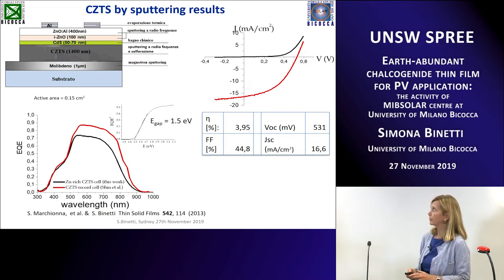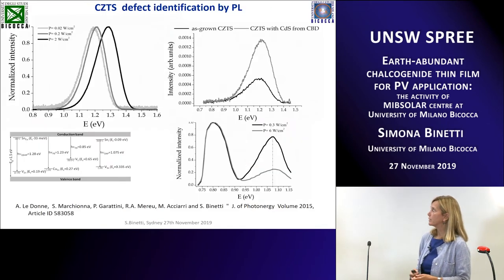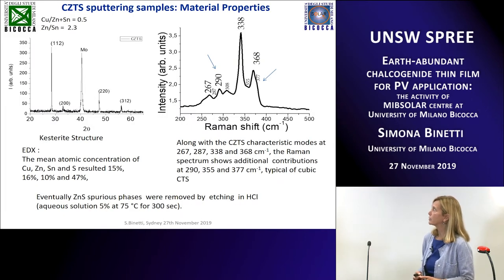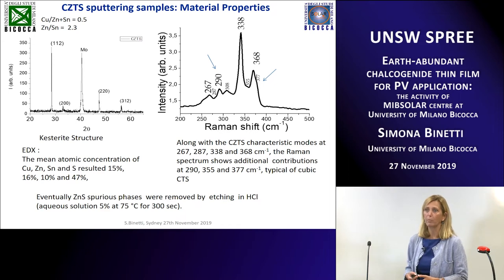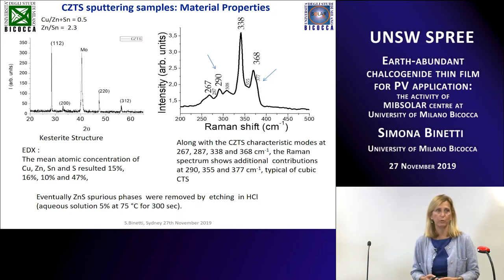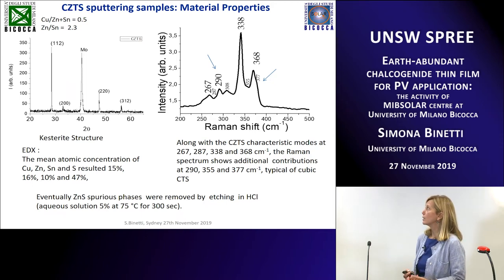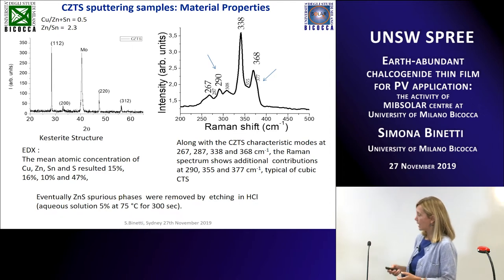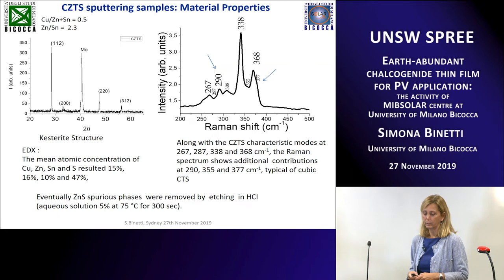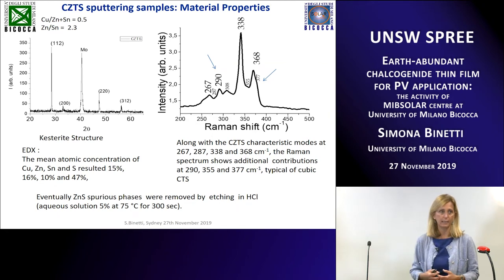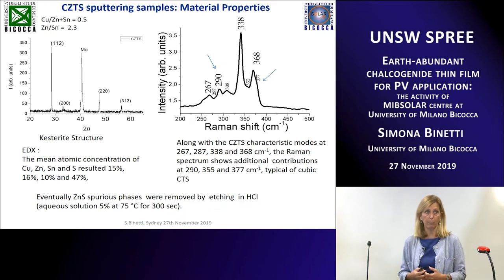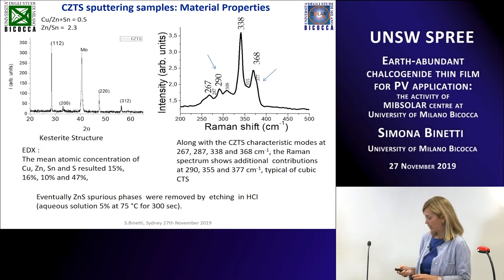to deposit Kesterite. Sorry, I forgot to say that, of course, before deciding to stop this activity on a sputtering system, we did a lot of characterization of our material to understand which types of defects were responsible for the efficiencies close to 4%. For instance, we performed Raman, X-ray diffraction and photoluminescence, and we saw that we had a lot of secondary phases, mainly the deleterious one, CTS. Also, it's important to underline that we cannot perform any KCN etching treatment before making our solar cell because this acid is not allowed in our system.